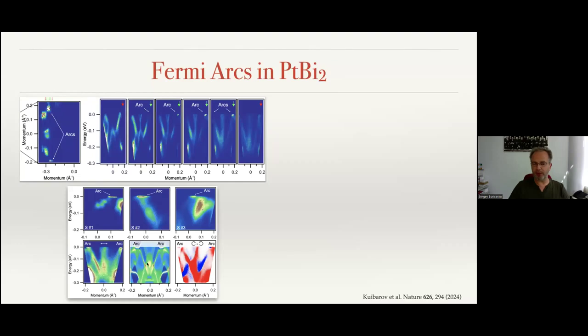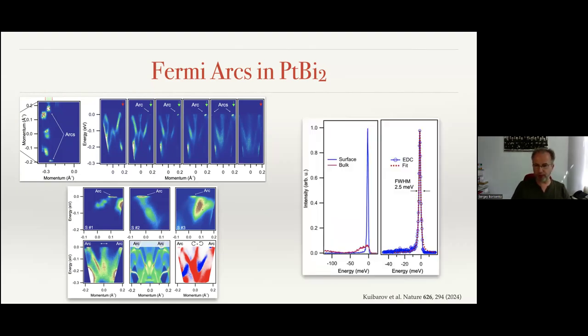So these are calculations along the cut, I think the vertical cut like this. And then you could see that experimentally and theoretically, they are located very close to the Fermi level. In order to give you an idea how sharp the peak is, I compare with a very decent EDC I showed you in the previous slide. That was from the bulk state, and this is the surface state which we observed. At that time, we thought that this is the record in the history of photoemission from the solid states, but I come back to this point later.